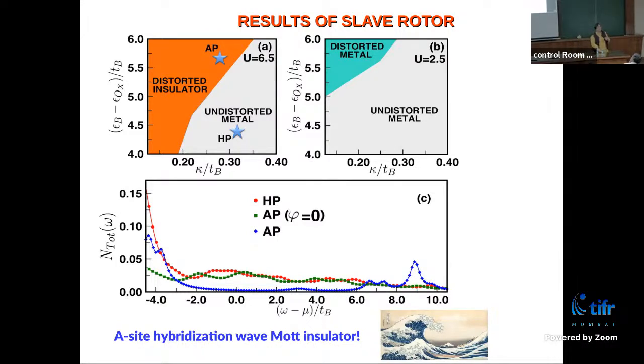Because what you are going to do by this distortion is to make nickel exactly half filled, nickel 2+, which is d8, and you have a crystal field splitting, so nickel d splits into t2g and eg, and with the d8 configuration you can actually show then the eg will be half filled, and since there is no ligand hole, nothing, you now, like a normal Mott transition, have to put a U to make that site insulating. And that's exactly what is happening as is shown with the spectral density plot. So we call them A-site hybridization wave Mott insulator. To explain that insulating state, what I need is a strong correlation effect. So that's why it's a Mott insulator.